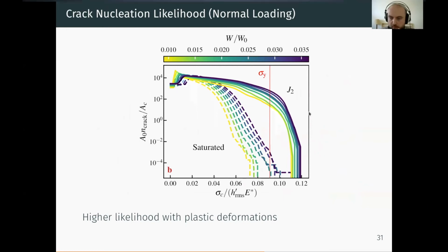What's interesting is that if we look in this part of the graph, let's say we take sigma c to be 0.1 here, we have a much larger likelihood of nucleating cracks than in the case where we have full description of plastic deformations, than in the case where we just say that the pressure should saturate at the hardness. And this is interesting because this saturated model essentially deforms elastically. This is a purely elastic deformation mode, and we assume there's a crack that is inserted at a given stress. So this is essentially a brittle material. Whereas the J2 case here, the von Mises plasticity case, has a phase of plastic deformation, and so it's a ductile material. And it's interesting to note, and it's a bit counterintuitive, that the ductile material has a higher chance of nucleating cracks than the brittle material.